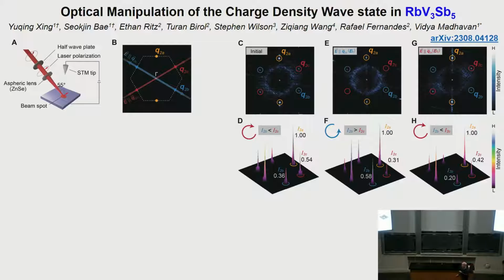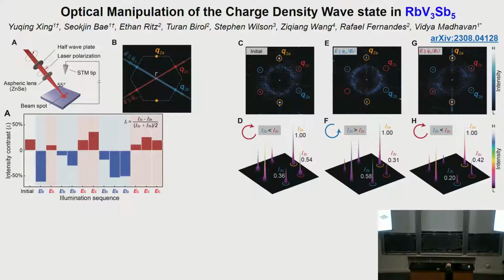So this optical switching of the chirality is essentially what she finds. And she can do this like that. It almost never fails. The chirality changes. And I asked her, how long can you keep this state there? She says she can go home and come back next day, do the measurement, and it's still there. All right. So that's basically what she observed. And it still doesn't say anything because what is the order parameter? She's still using the height, the intensity difference. Of course, now she can control optically the intensity difference. Okay. So I said, let's try to find out what is exactly ordered.